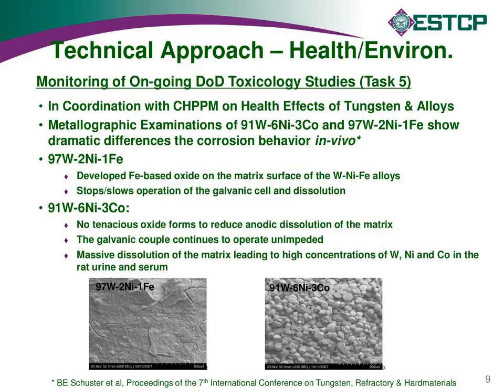Strange test. I mean, in one case it's becoming bioavailable, in the other case it's not. Yeah, the other case is the tungsten nickel iron alloy. So there was some dissolution early, and again, Brian will go into more detail later. But what happened was essentially you ended up with this iron oxide coat that very quickly showed up on the pellets, and kind of shut off the diffusion process fairly early. So the nickel levels quickly dropped in the blood and urine samples, for example, in the rats. And those rats survived the 2-year study. So it was kind of interesting that the nickel iron alloys, which are typically the older family of alloys, did not appear to be hazardous.